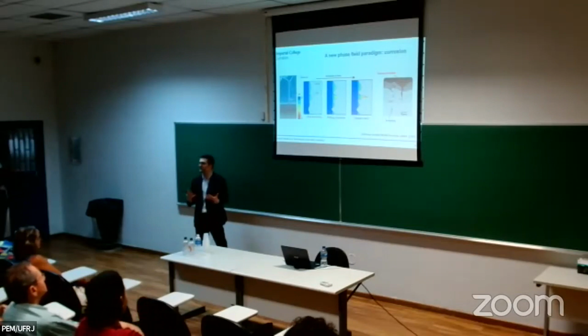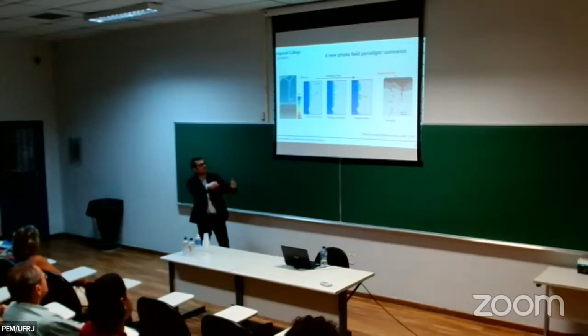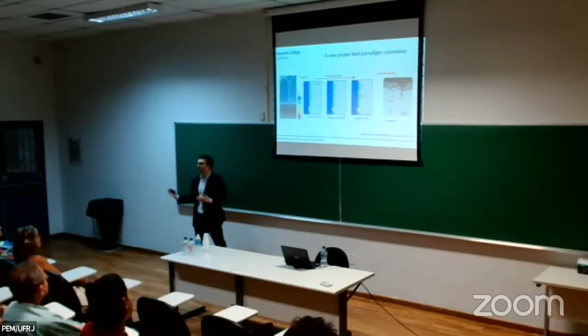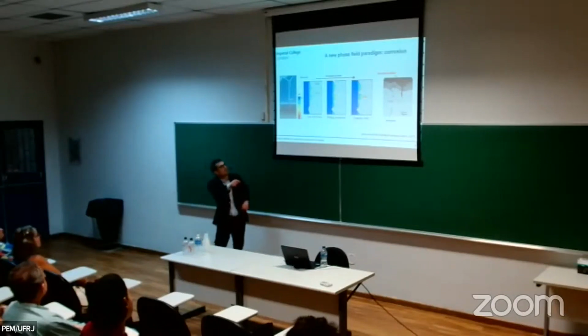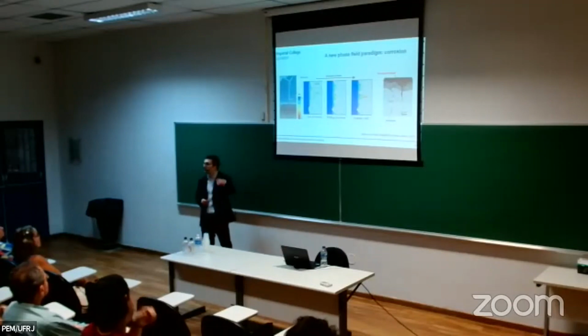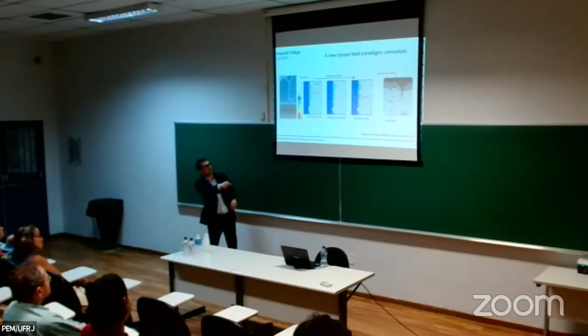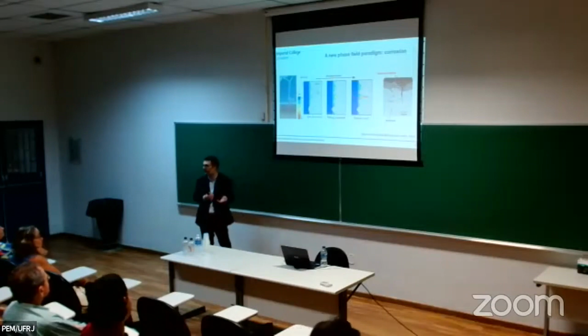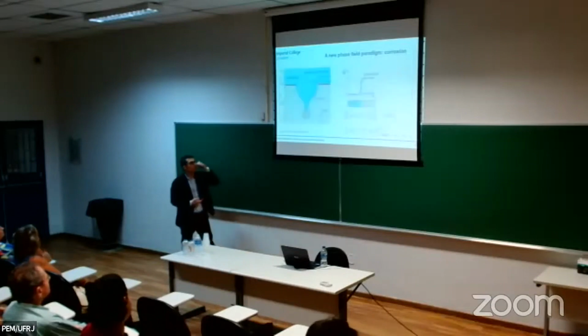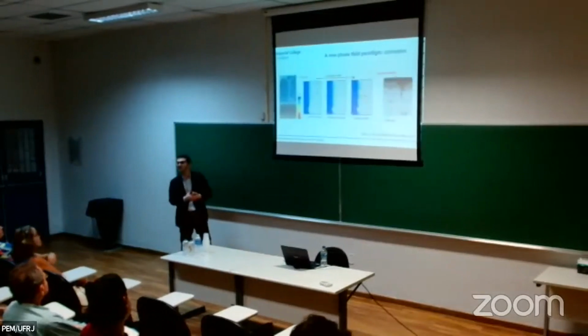If you want to resolve the physics of this problem, not only do you need to couple the chemistry, the mechanics, and so on, but you need to couple all of these with the interface morphology. The shape of those pits is going to be determined by the local chemistry and mechanics, but the local chemistry and mechanics are themselves dependent on the shape of those pits. So the pH will change drastically inside a pit. As you know, a pit is a stress concentrator, so it becomes very sharp and the stresses are going to be higher. Everything is very strongly coupled. But again, this seems like a very suitable problem to tackle with interface modeling and multiphysics modeling. So we decided to do that.